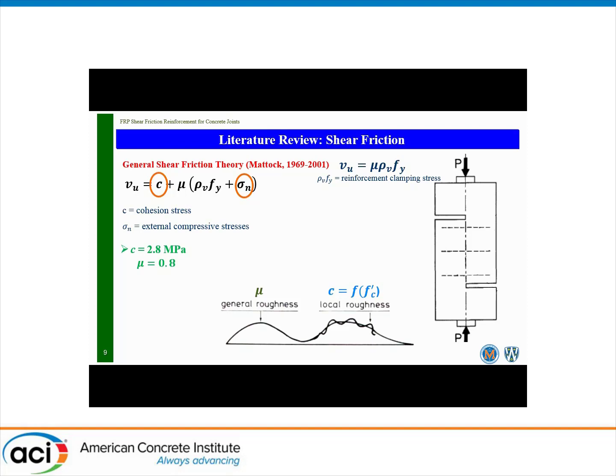After several iterations, research has been carried out since the 60s until recently, applying several developments and improvements to the shear friction theory. In its most recent current format, the shear strength is attributed to the cohesion of the concrete, then the coefficient of friction multiplied by the clamping stresses, where the clamping stresses come from the amount of reinforcement times the yield strength of the steel, plus credit for any extra external clamping stresses due to other sources.